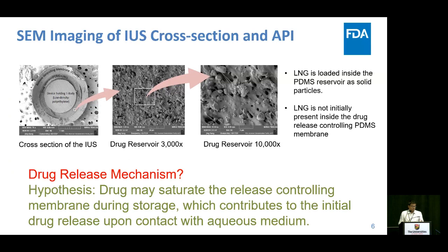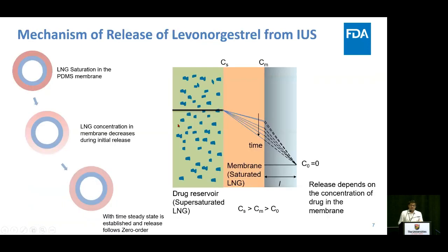So from here, what can we say about the mechanism of drug release? We came up with a hypothesis with the available information that the drug may saturate the release controlling membrane initially during storage, and this contributes to the initial drug release upon contact with the release media. Based on our hypothesis, this is the concentration time profile. We hypothesize that the drug release depends on the concentration gradient in the release controlling membrane, in this image, this one. And as time passes, steady state is established when the amount of drug going out from the membrane equals the amount of drug coming in from the supersaturated drug reservoir.